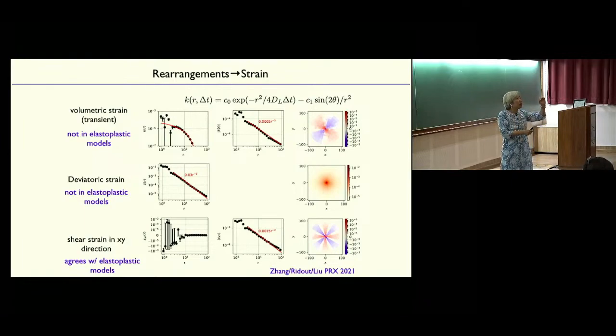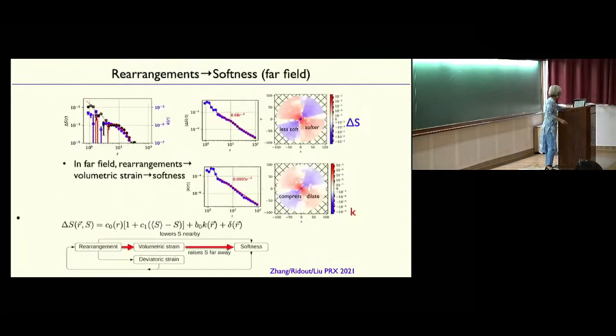due to a rearrangement. Okay, put the rearrangement at the origin. What you see is that the magnitude of that volumetric strain decays like 1 over r squared in 2 dimensions. And if you look at the angle dependence, it has this form. Okay, if I look at the deviatoric strain, it again decays like 1 over r squared, but it's isotropic. And I can also, this is directional. I am shearing in a certain direction, or I'm pulling on the pillar. Okay, there's a direction in here. And I can look at the shear strain in that direction. And that has a typical quadrupolar form, very famous in studies of plasticity.